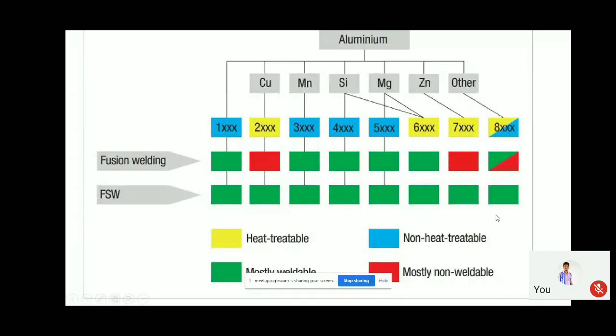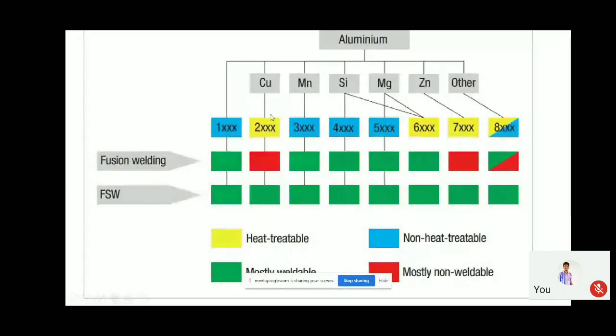Next we move to friction stir welding, one of the emerging green welding techniques. This technique was widely developed for aluminum alloys. There are 8 different series of aluminum alloys, based purely on the addition of alloying elements. As I told you previously, the 2 series and 7 series materials are not possible to weld with conventional welding processes because they are heat treatable materials. The only possible way to weld aluminum alloy 2 series and 7 series is the friction stir welding technique.